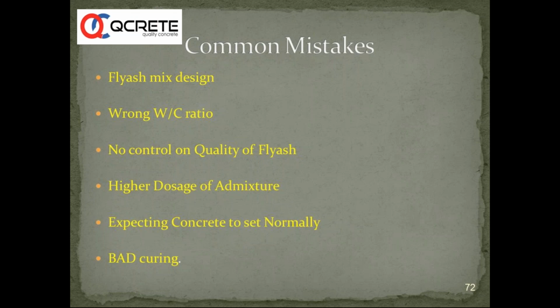And you should not expect concrete to set normally. When you are using OPC plus fly ash, for example in columns or beams or slabs, it will set, it will harden, but the rate of gain of strength in the initial times is lesser, as we have already discussed. So you cannot just de-shutter this concrete like that. You need to have some patience. You need to show some patience as a customer because you are getting a package of benefits.